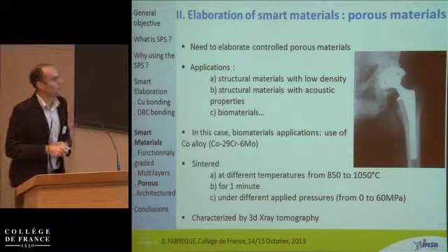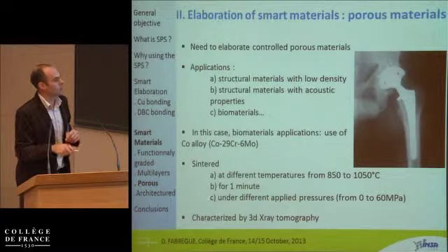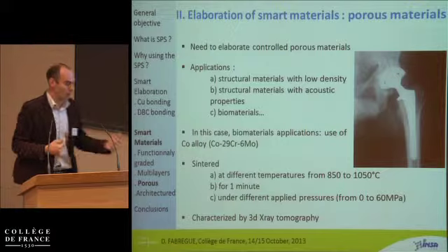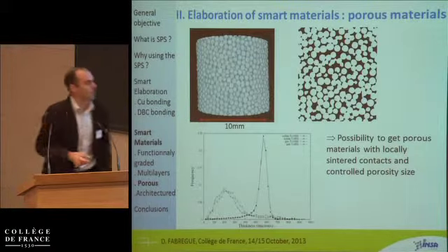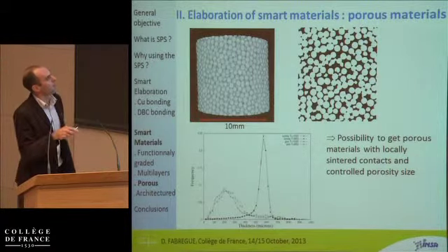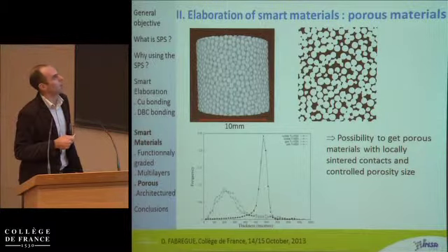We use another very well-known biomaterial, which is a CCM alloy. This is a cobalt-based alloy, and we sinter that at different temperatures and different pressures, and we look at what happened in terms of microstructure and actually macrostructure. So that's the kind of samples you can get.